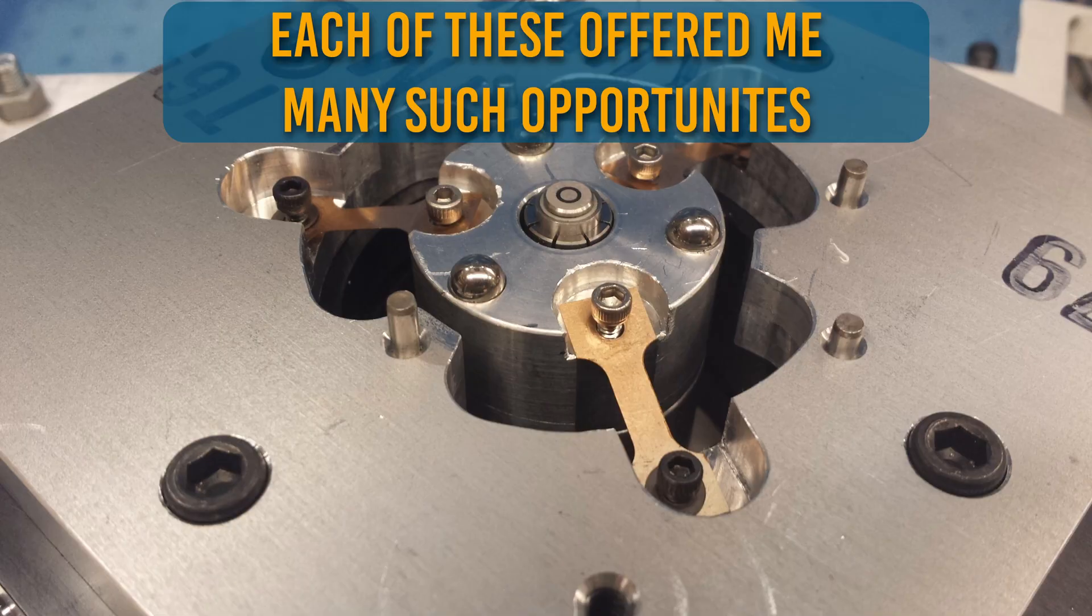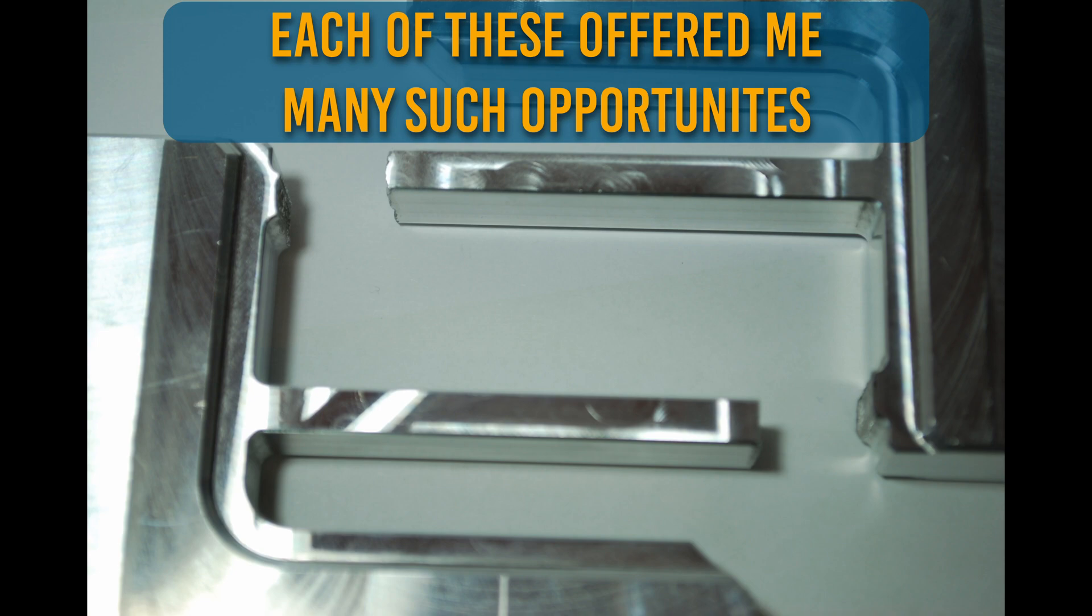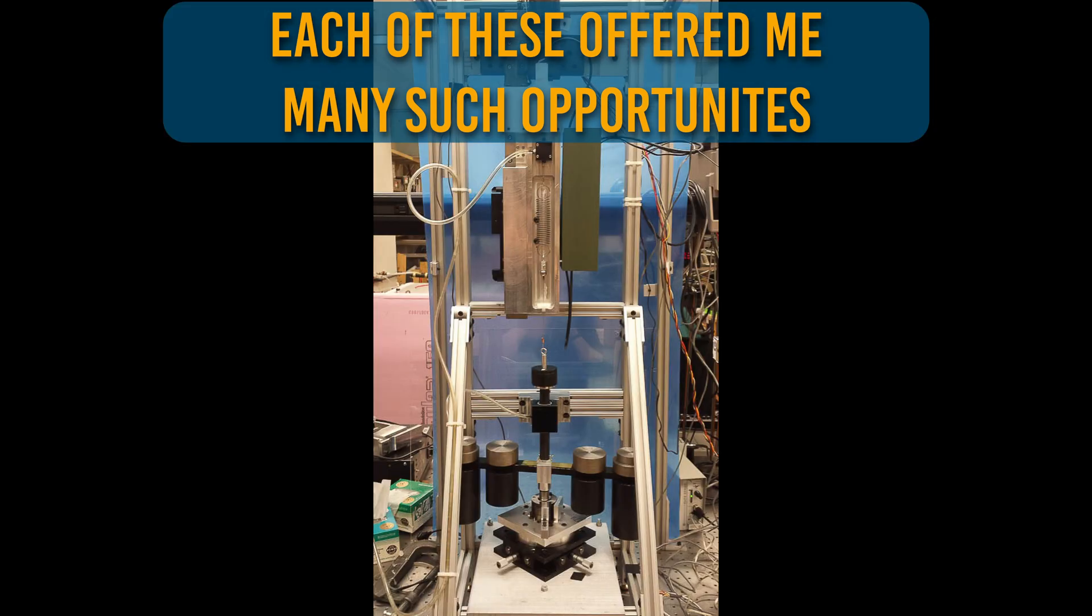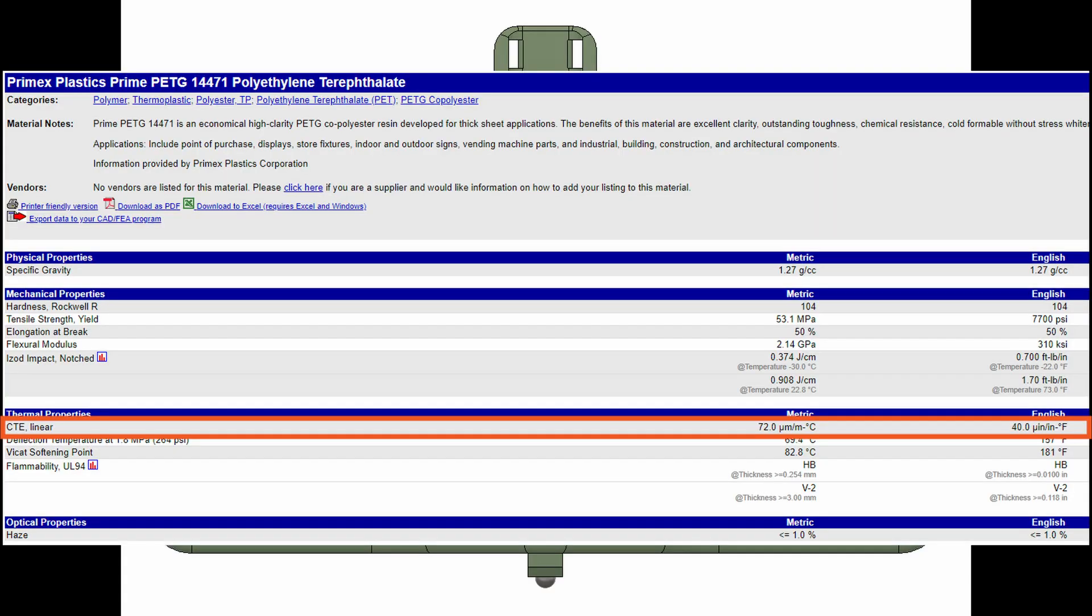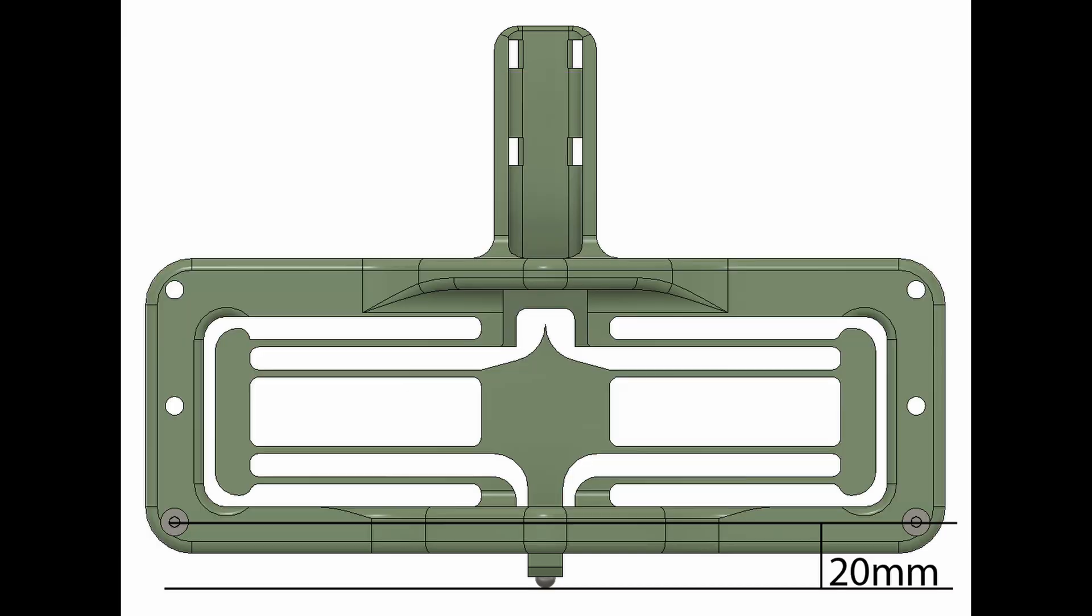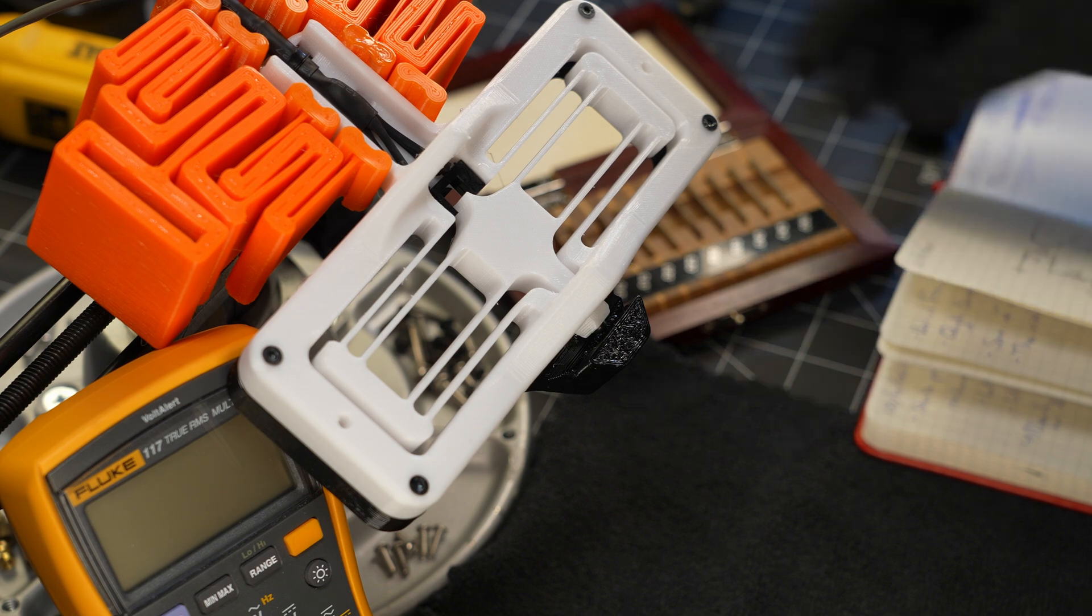But one thing I love about my line of work is how good data is at proving me wrong. The coefficient of thermal expansion, or CTE, for PETG plastic is around 70 parts per million per degree C. And with the 20mm length it's acting over, I expected to see a temp sensitivity in the ballpark of 1.5 microns per degree. Spoiler alert, it wasn't.